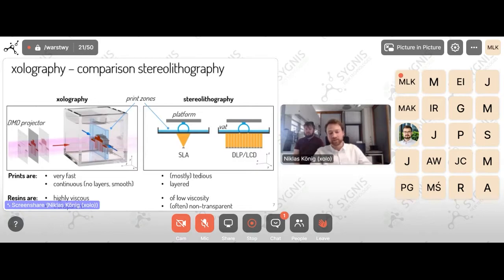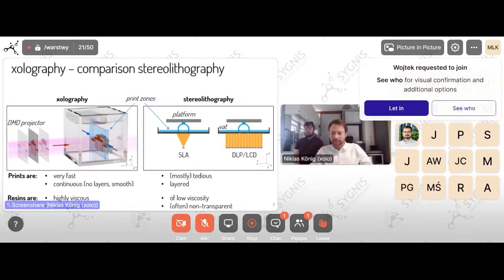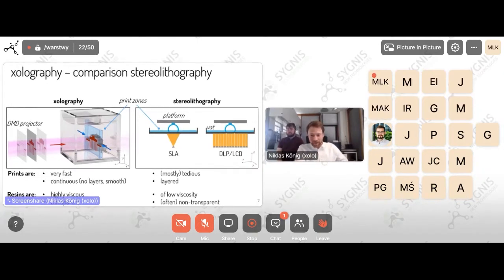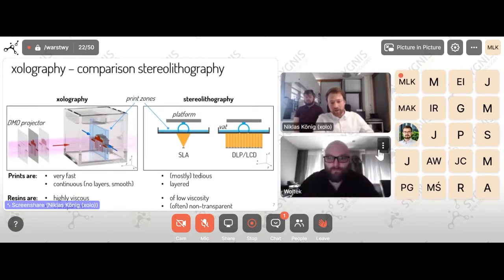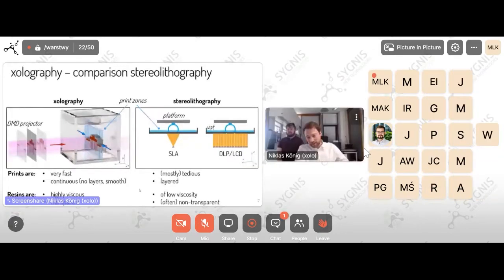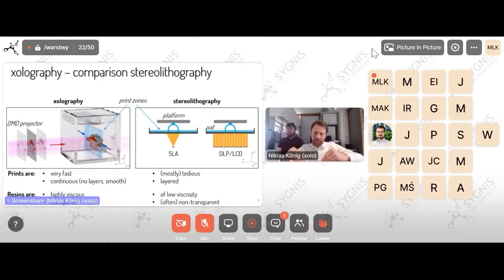And that's why we're actually that fast, because instead of letting the resin flow into the printing zone, we let the printing zone go through the resin. And yeah, that's basically the whole trick about it. And this enables us also to use highly viscous resins, because in standard stereolithography, you use low viscosity resins, because they always have to flow into this print zone. And sometimes people are even heating up their photopolymer to make it less viscous, to be able to flow in reasonable time into this cavity.